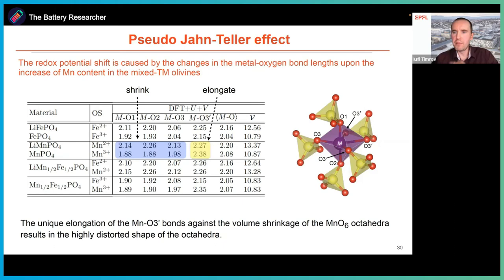And by the way, this also happens because these bonds, manganese O3 prime, are connected to the phosphorus tetrahedron via edge sharing. And it is known that phosphorus tetrahedra are very rigid. And that's why this affects the behavior of the bond lengths when we delithiate or lithiate the material. While the other two or three are not edge sharing, but corner sharing, and that's why they can shrink.